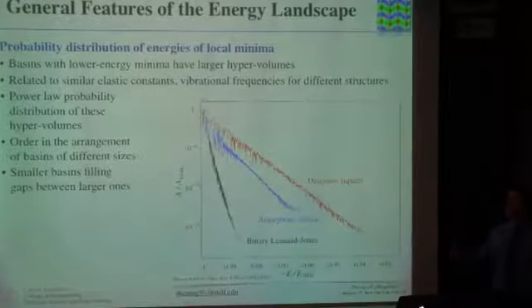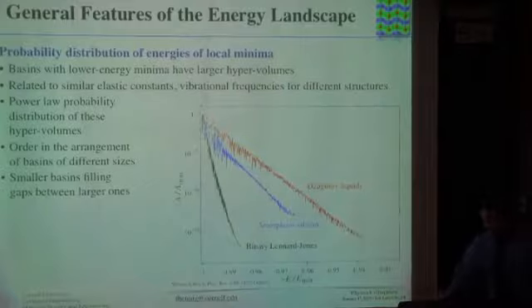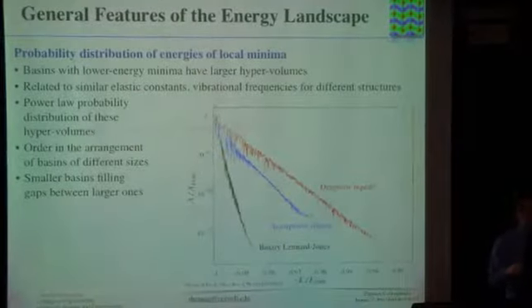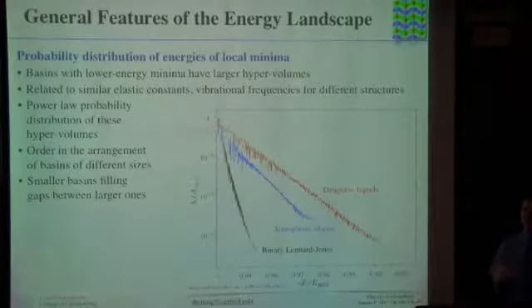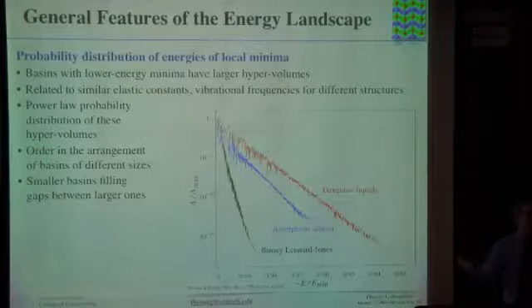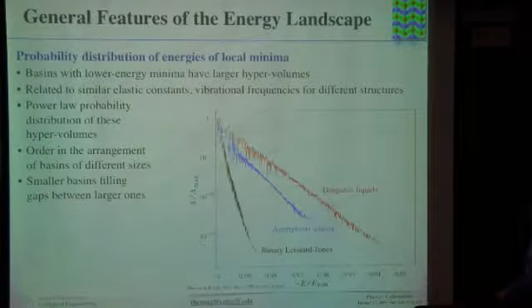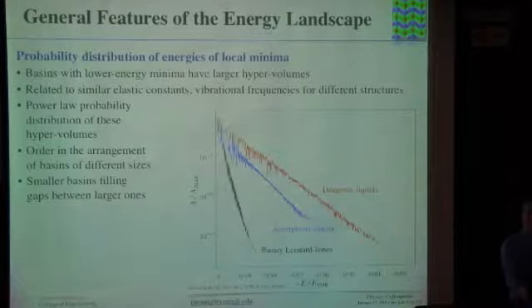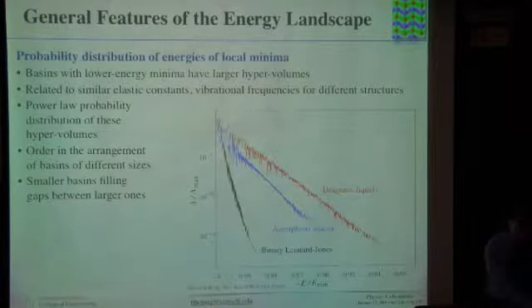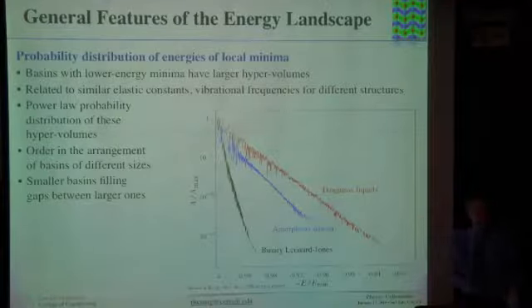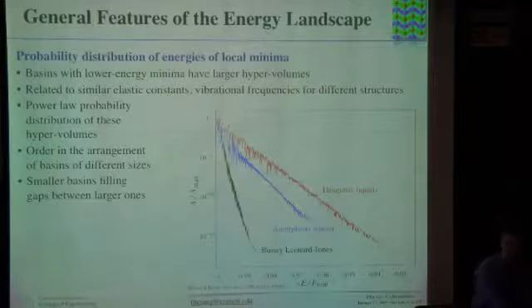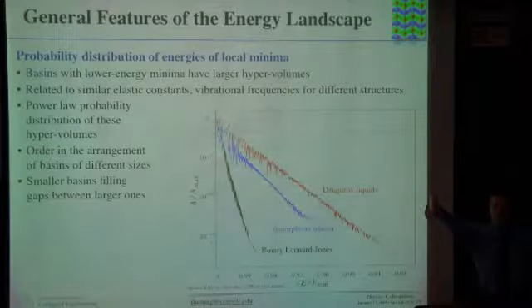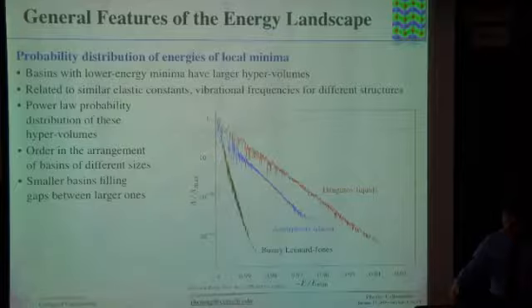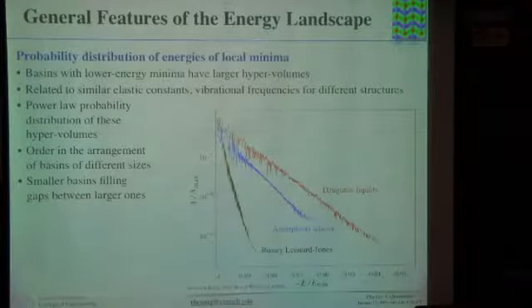That means if I stretch my materials, if I move my atoms around, the energy change is somewhat similar for all these different minima in my configuration space, which means that all these minima are parabolic near the minimum with a similar curvature. And if you think about all these little parabolas in space, and they connect somewhere with these barriers in between, that means if a minimum is very deep, it's more likely to have a very large basin. And that's exactly what Massen and Doye showed here in their work.